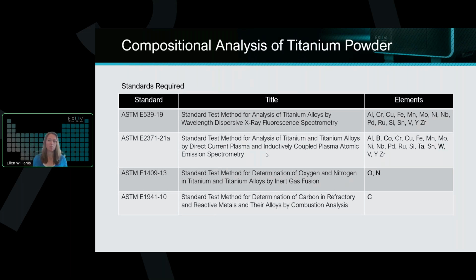But for titanium powder, let's just look at some of the standards that you might use in order to test the elemental composition. So you may start with the first standard there. You may have WD-XRF, and that does give you a range of metallic elements by following that standard. But for particular industries or applications, there may be other trace elements that are below the detection limit of XRF. And so you may have to use the second standard, which is that ICP, optical emission spectroscopy technique that I mentioned earlier. So then you're dissolving the powder into acid to do your ICP to get some of these other trace elements, maybe boron, maybe tungsten.